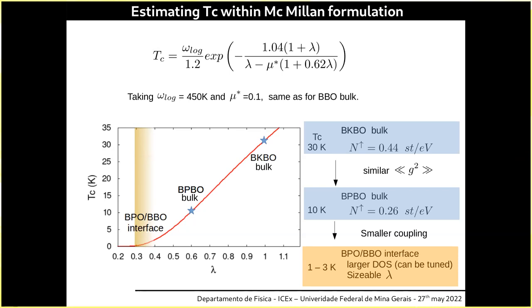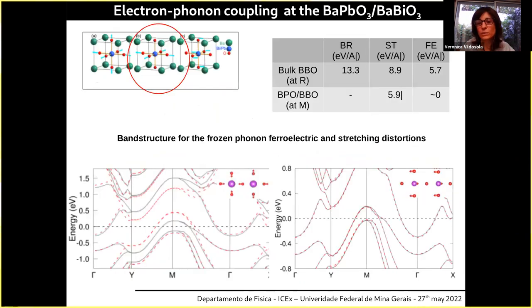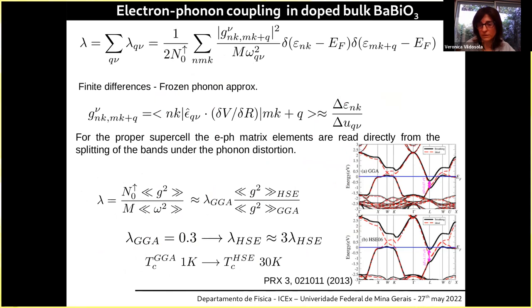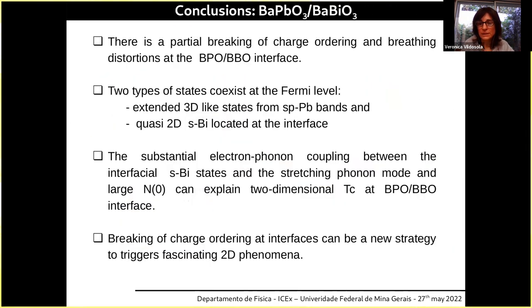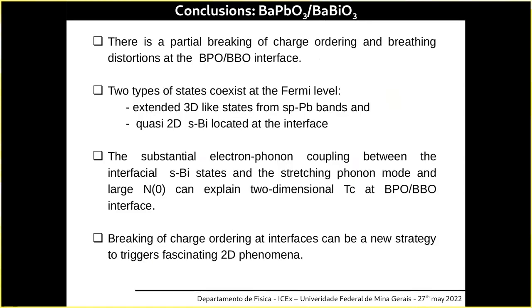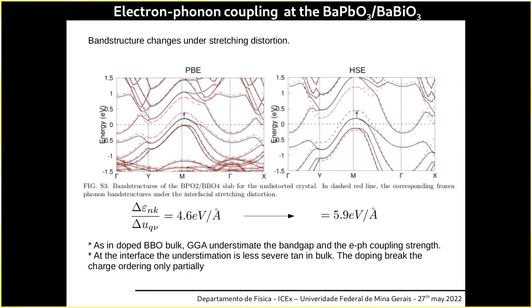If you don't mind, another question, please. This is a technical question. If you use HSE hybrid functionals, I'm working with similar samples with doped BBO, and I'm having real trouble calculating those band structures using hybrid functionals. Yes, it's horrible, a highly costly computational effort. That is why we always do things with GGA, and for the smaller cells we do both together to be confident for the larger cells, where it is impossible. Unfortunately we have to do hybrids because GGA doesn't correct the gap for these bismuthates, and you need the gap.